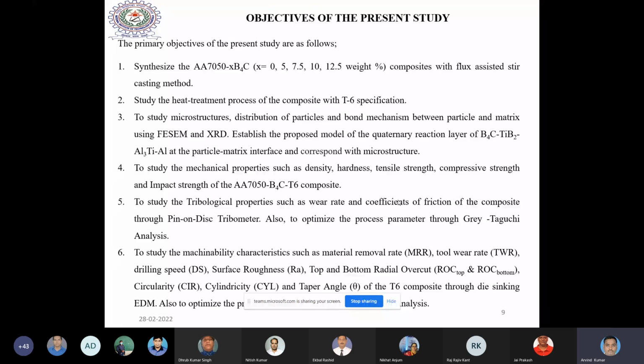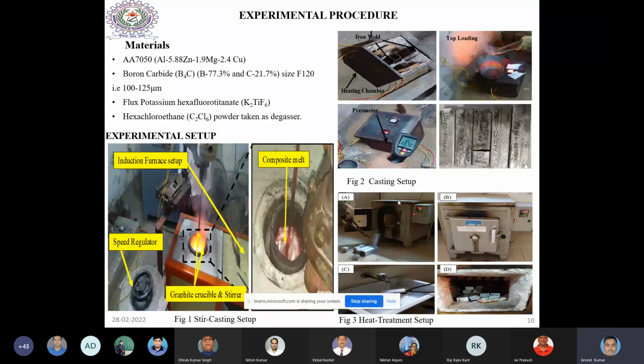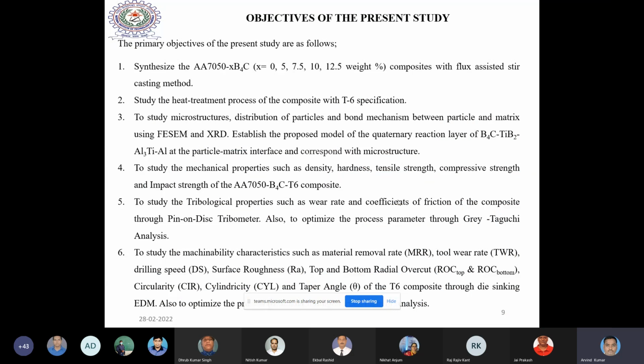Then we have gone for several kinds of mechanical testing, right from density, then hardness, tensile, compressive, and impact tests. After that, we have tested the tribological property of the developed composite material, and that was optimized by an optimization method, and there it has also proved that the method we selected was good. And then at last, we have also done the machinability of the developed composite. And these were the outputs through electro discharge machining.